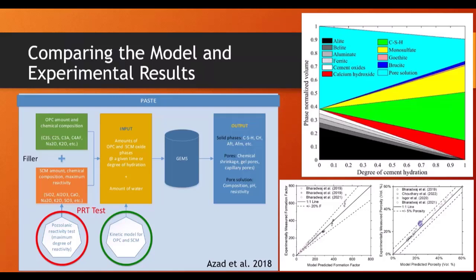I want to be super clear when I say this. This is not a strength activity index. This is not just throwing something into a calorimeter and hoping for the best. All right, this is not doing some other crazy test that's been derived. It's a very simple test that we do to get a quantitative value of how much of that pozzolan actually reacts. We put that into a kinetic model, and we can actually predict the performance of those systems.